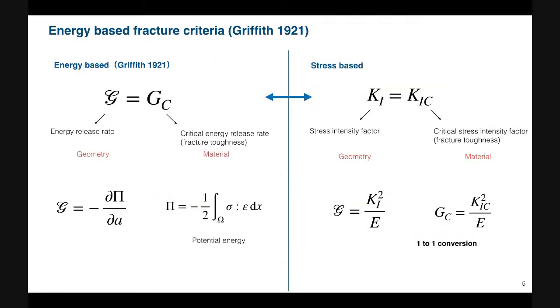Okay, so now let us go back to the original fracture criteria, which was proposed by Griffith in 1921. The stress-based criteria is actually derived from the energy-based criteria. In the energy-based criteria, we compute a quantity called the energy release rate, which is defined as the derivative of the potential energy with respect to the crack growth. When it reaches the critical value, the crack propagates. The energy release rate can be converted to the stress intensity factor, so the critical stress intensity factor corresponds to a critical energy release rate. There's a one-to-one conversion. The left-hand side is geometry, and this quantity requires an initial crack geometry to compute, and the right-hand side is a material property.